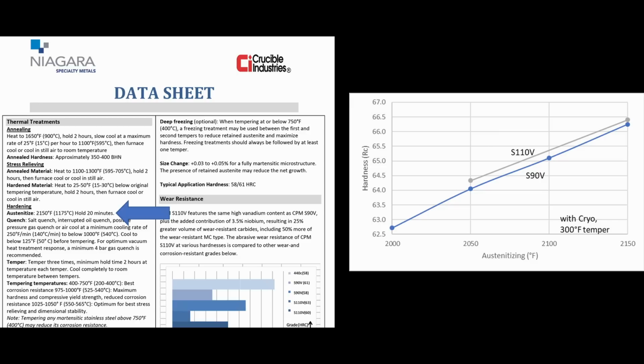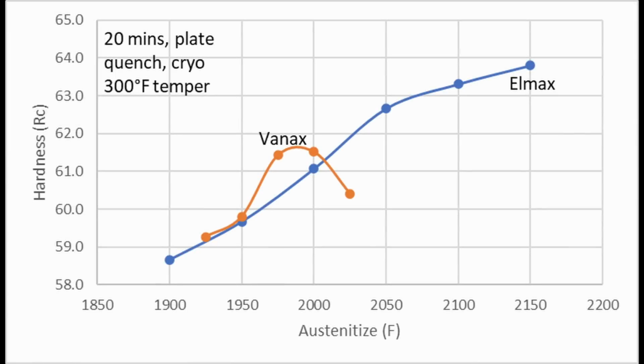So any commercial heat treating facility following the datasheet may have too much retained austenite. Some steels like Vanax and LC200N are difficult to heat treat beyond 58 to 60 Rockwell. So the heat treaters are forced to austenitize at the very peak of the austenitizing curve, where it is easy to overshoot. I have a chart here showing Vanax, the steel that's difficult to heat treat to high hardness, and Elmax, the steel that is easier.